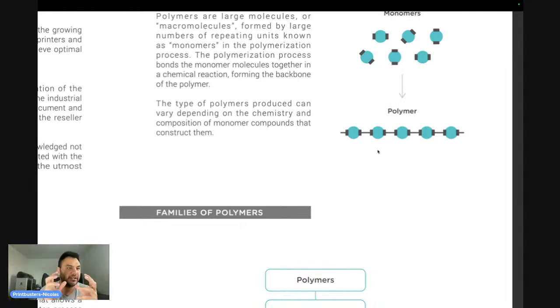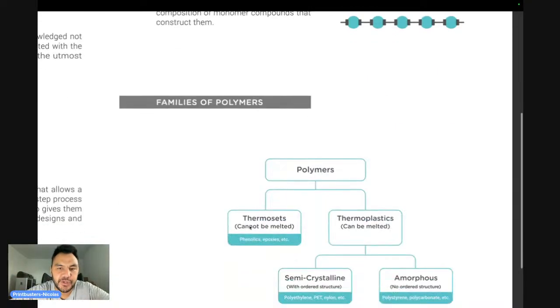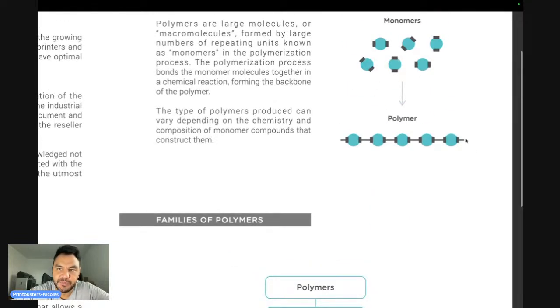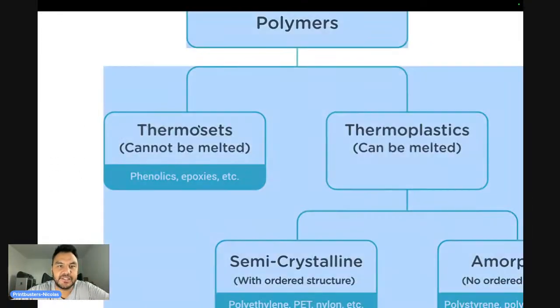And so that's the reason. You break the secondary bonds, you reshape it, and you recreate the secondary bonds, etc., etc. And you can do that multiple times. The problem with thermoset is that there is also some polymer like this, but in between the polymers, it's not a secondary bond. It's actually also a primary bond. So all the polymers, all the spaghetti, are also connected with each other with a primary bond. So they are cross-linked, basically. I think that's what it's called. If you have heard of vulcanization, it means you cross-link the different polymers together, right? And if you break that primary bond, then you completely destroy the part, right? You're basically breaking the primary bond, so there's nothing left. So you cannot recreate this primary bond. Okay, so hopefully that makes sense on the difference between the two.